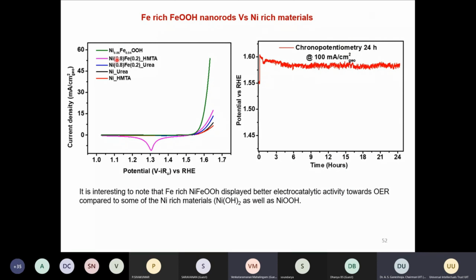So we compared the activity of this material with nickel-rich material. Nickel-rich materials, for example layered double hydroxides, are excellent materials for the oxygen evolution reaction. We tried to prepare this nickel-rich material, for example nickel 0.8, iron 0.2, using HMTA, urea, different bases. We compared the results with our nickel 0.06 iron oxyhydroxide material. And what we found is that, still, compared to nickel-rich material, this nickel 0.06 iron oxyhydroxide material shows better activity.